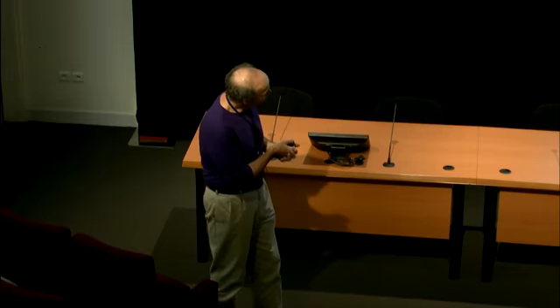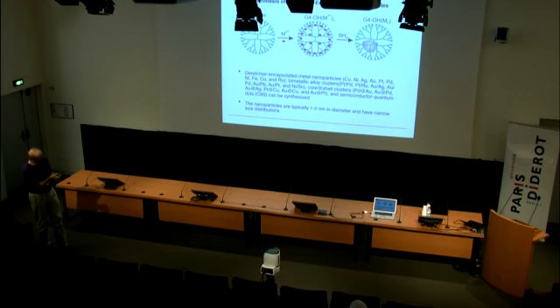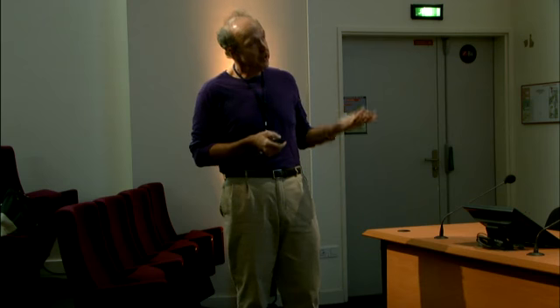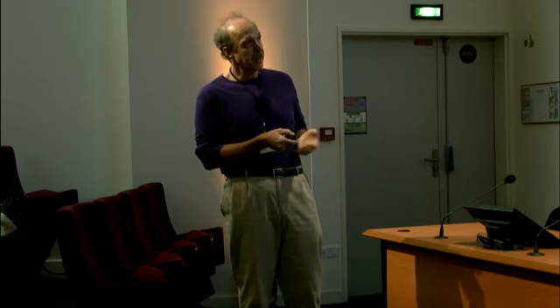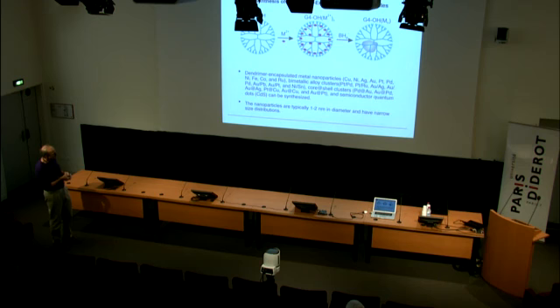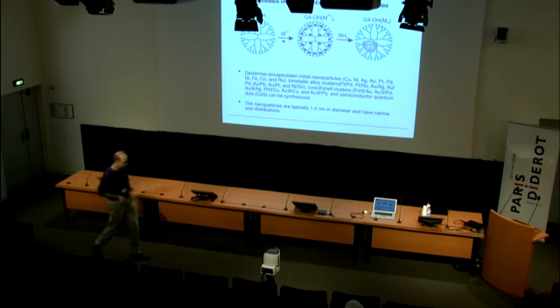So they're pretty monodispersed particles because it's a template synthesis, and the surface of the particle is accessible for catalytic reactions. And so not only is it possible to make monometallics, but we've made alloy particles of various sorts, core shell particles, and we even have one paper on cadmium sulfide. So you can make semiconductors as well.